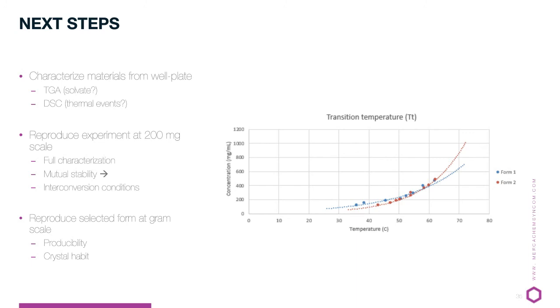So there are conditions in the screen that allowed form 1 to be the most stable form to grow. Certain cooling conditions go to form 2, and the mixture is also obtained. It didn't have enough time to convert into one form. When we did the test for the interconversion conditions, it was a slow process to go from form 1 to 2 or the other way around.